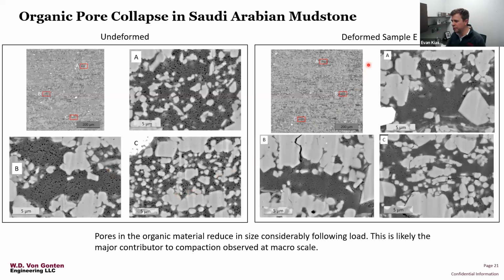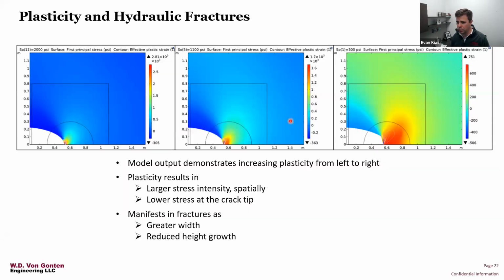Following the deformation of the sample, you can see a clear decrease in the volume of these pores. By looking at different locations in the mosaic, we can see this is definitely not a localized phenomenon, but a very compelling reason for the compaction we're seeing.